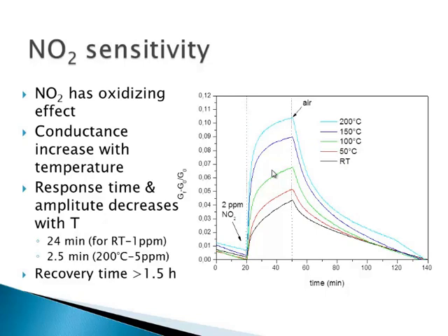And here the response time, of course, decreases a lot from 24 minutes to 2.5 minutes at 200 degrees at 5 ppm. But as you can see, the higher the concentration, the higher the response, and the recovery time is still really high.